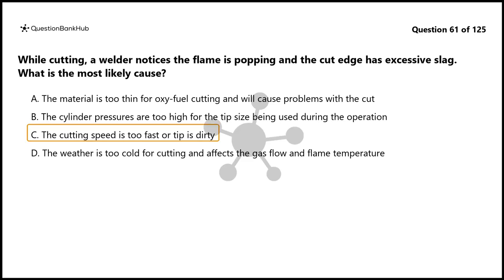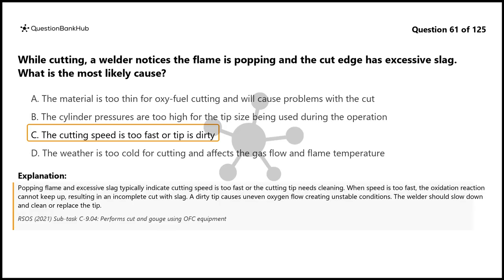The correct answer is C. The cutting speed is too fast or tip is dirty. Popping flame and excessive slag typically indicate cutting speed is too fast or the cutting tip needs cleaning. When speed is too fast, the oxidation reaction cannot keep up, resulting in an incomplete cut with slag. A dirty tip causes uneven oxygen flow creating unstable conditions. The welder should slow down and clean or replace the tip.